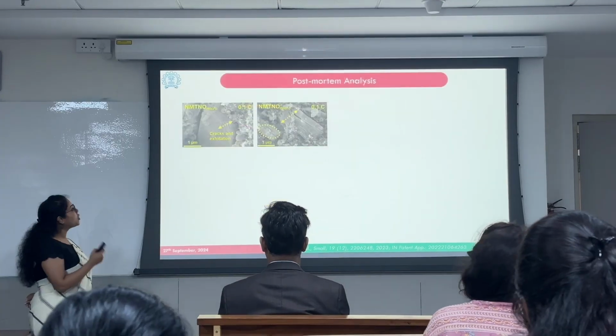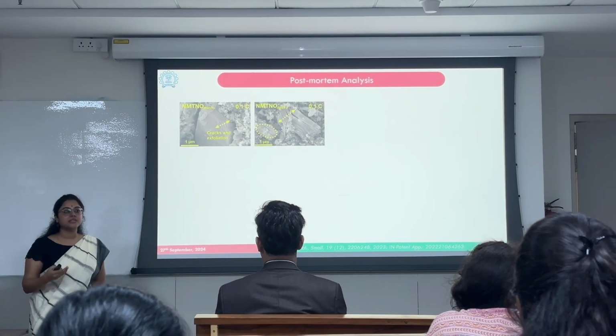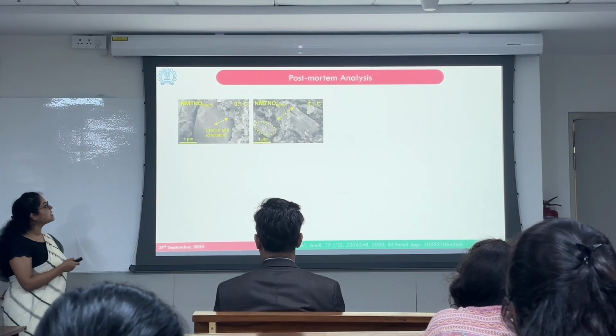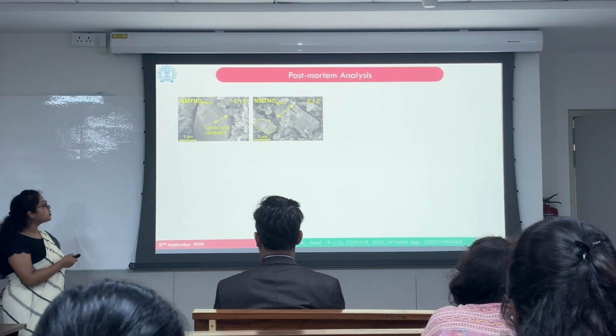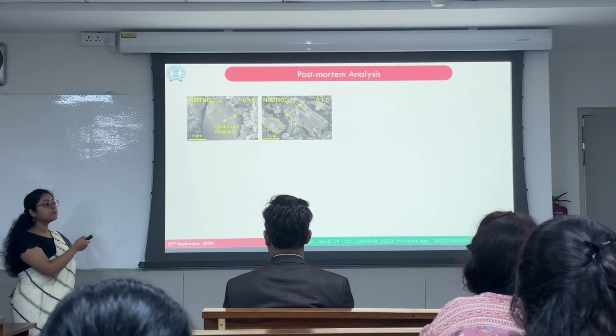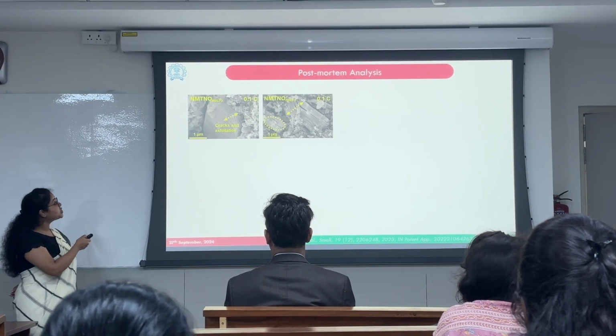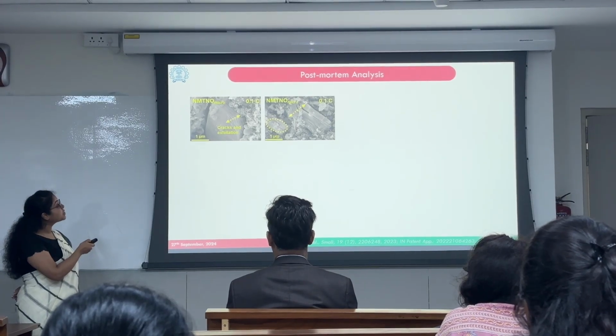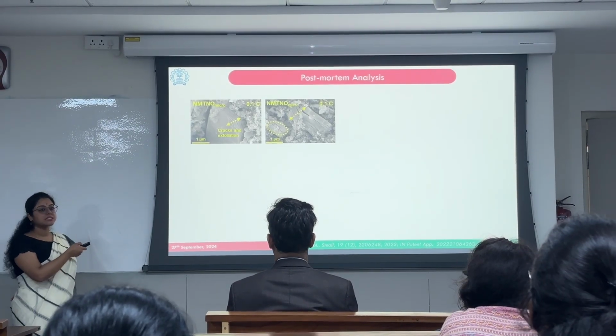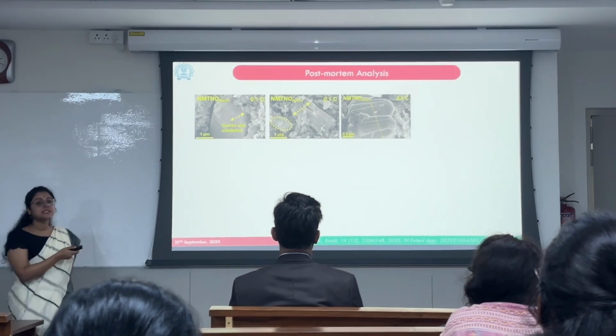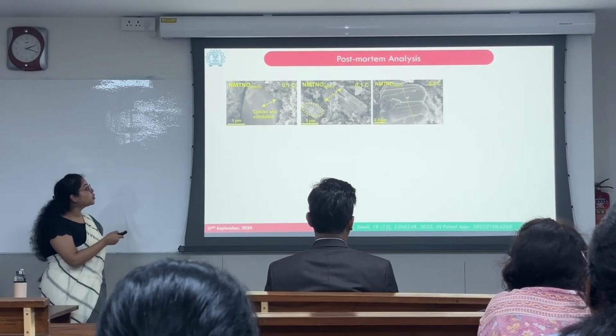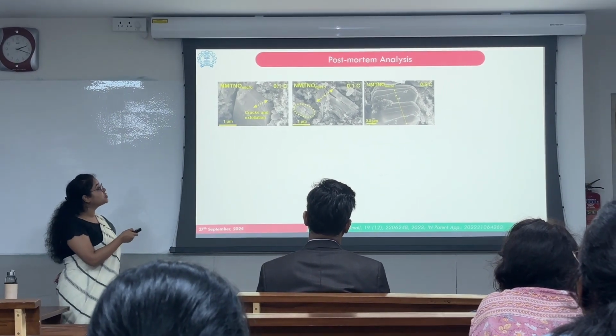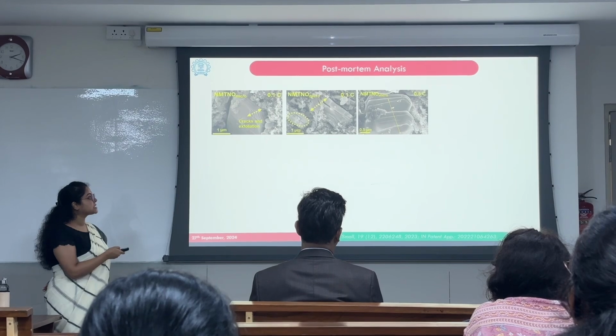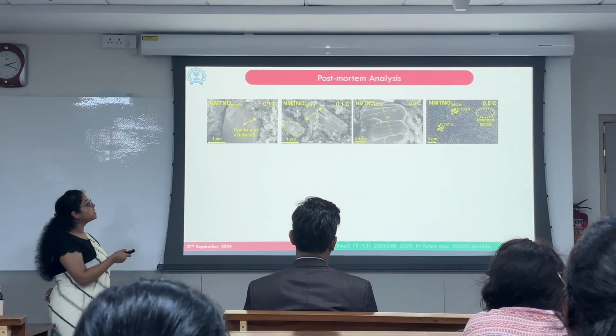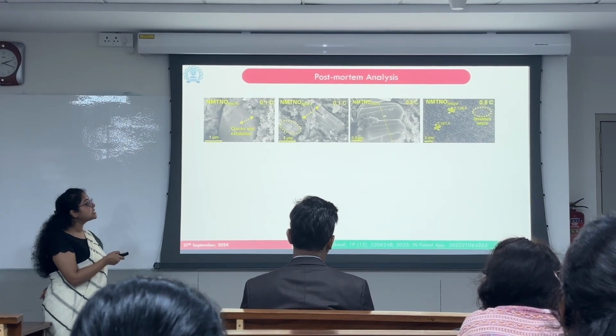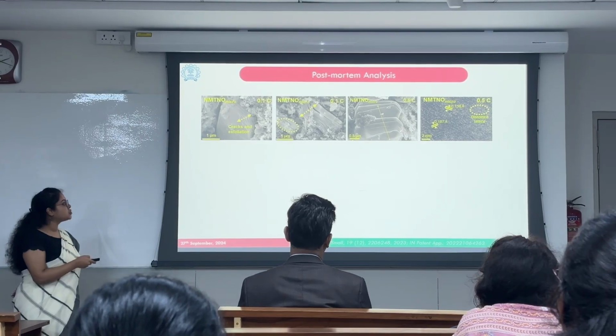We then saw the morphology by collecting the electrodes after 10 and 100 cycles at 0.1 C, and we saw that just after 10 cycles, the NMTNO micro initiated cracks and exfoliation, which aggravated further after 100 cycles, and in fact after a higher C rate of 0.5 C, we observed that it broke down into multiple sheets, which was also evident through the high resolution TEM, where we could easily see the distorted lattice fringes.